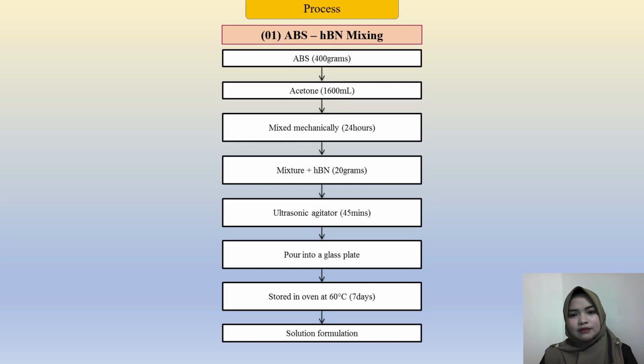First is ABS HBN mixing. Start with the combination of ABS with acetone mixed mechanically for about 24 hours, and mix with HBN at 20 grams, and goes to the ultrasonic agitator for about 45 minutes, and then pour into a glass plate and store in an oven at about 60 degrees Celsius for 7 days and become solution formulation.